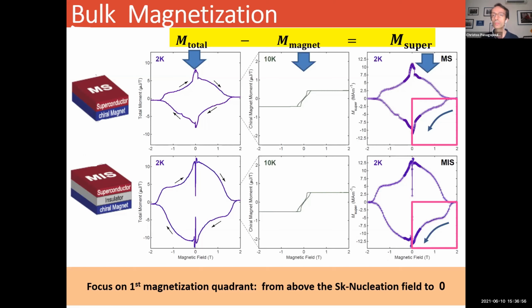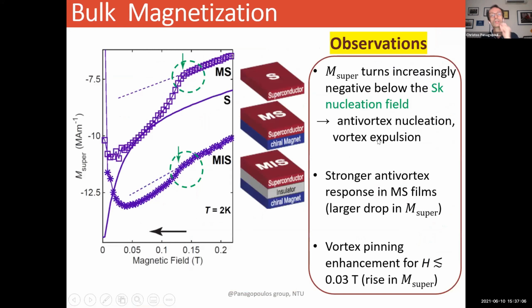So we will focus on this behavior as we go down here. And we will be looking at the superconducting component, which is the right-hand side column. By looking at this quadrant, we see a deviation from the saturation magnetization downwards, which I point here in green circles for the MS and the MIS sample. And for reference and comparison, I'll show you the behavior of the pure superconductor shown here as S.